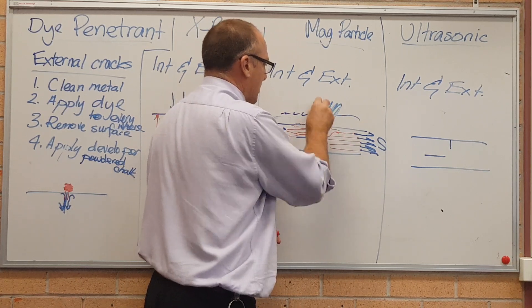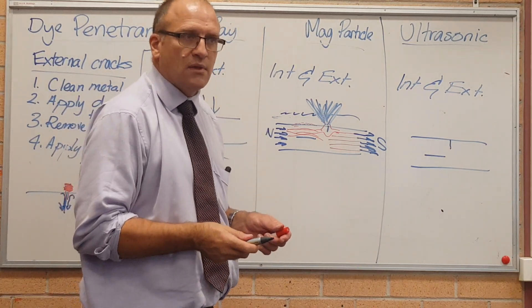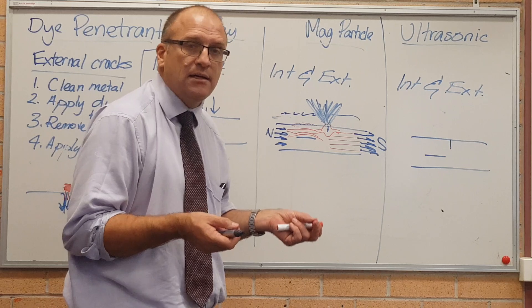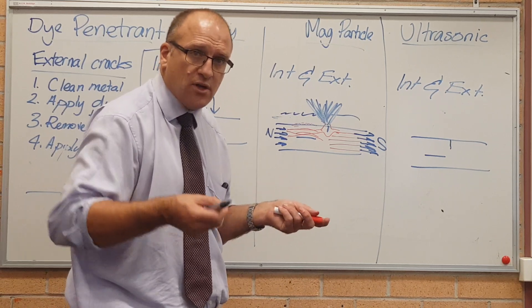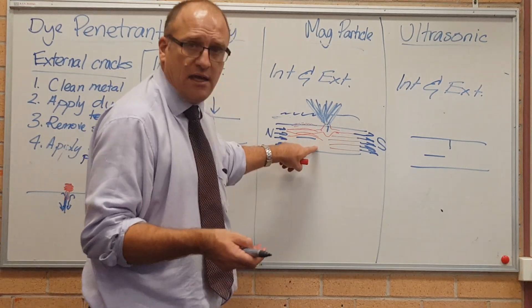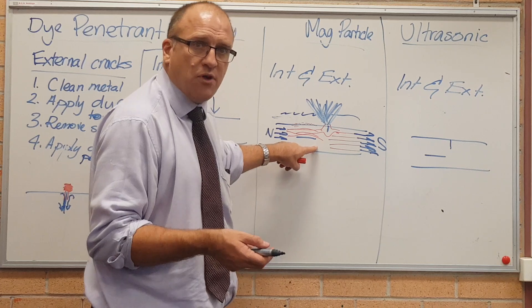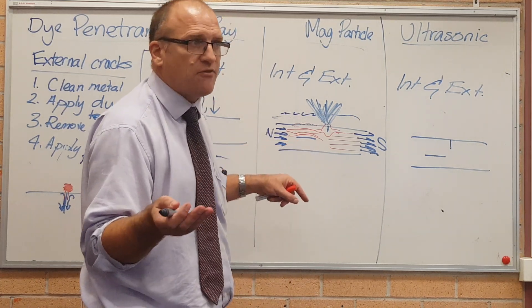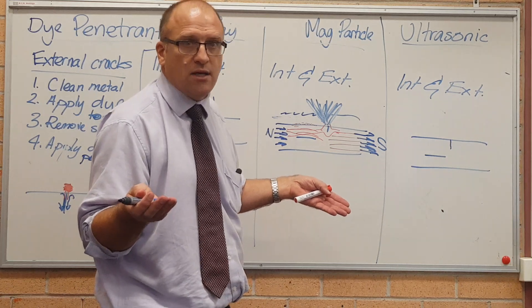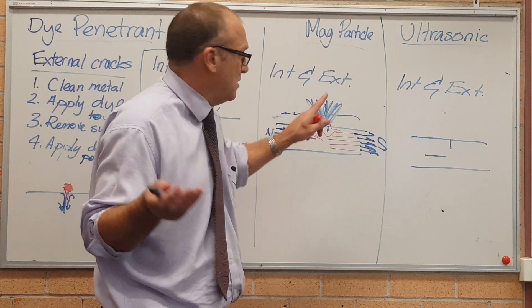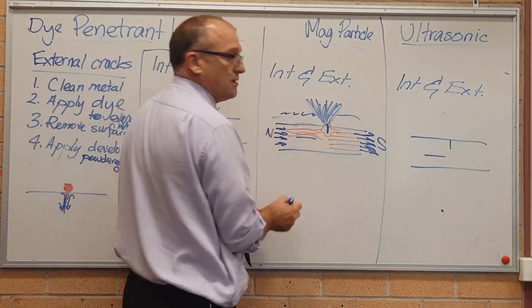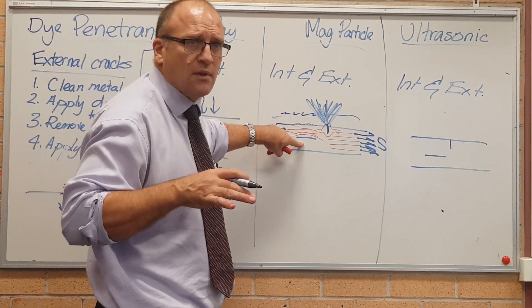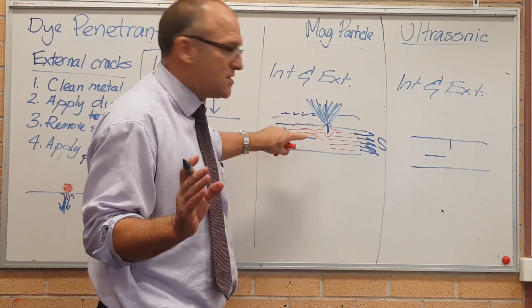Things that are 90 degrees to the field show straight up like nothing else. If I've got kerosene over that with magnets, they literally stick out there like that. You cannot miss the fact there's a defect. When you make steel, it's sometimes got bits of the slag inside it and the stuff from the furnace, the silica. The silica, the slag, the calcium from the blast furnace gets trapped in it, gets rolled into the steel and comes through in between all the grains. That's really bad if you want to make tin cans or if you're trying to form a car body panel, because it's a stress raiser that initiates fracture. Because ceramic obviously, if you've got sand and steel, the sand will just shatter when you try to stretch it. So this is great for detecting cracks at 90 degrees to the surface. It's only so-so for detecting cracks that are parallel to the field. There's a common theme here, I hope you've seen. So that's mag particle tests.